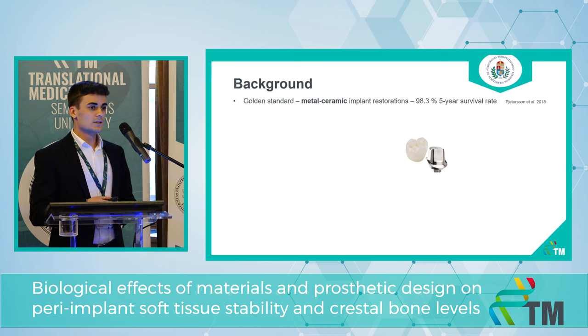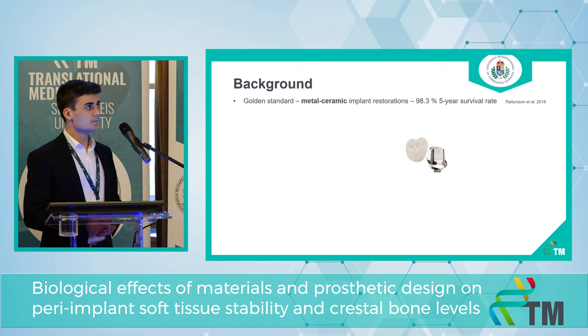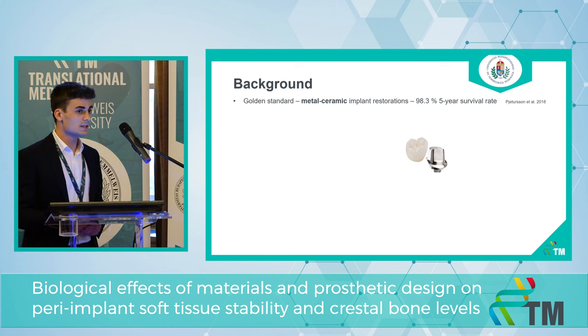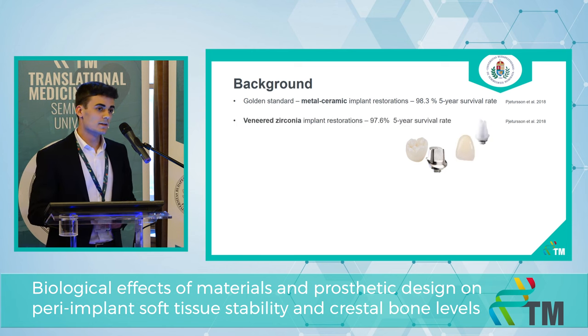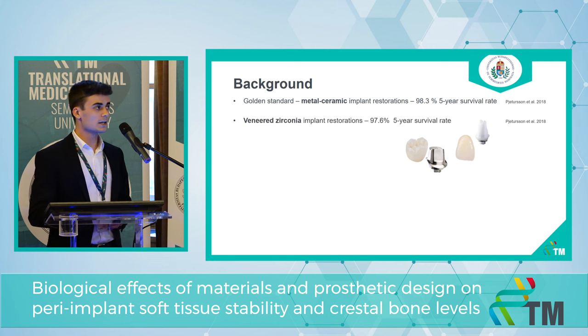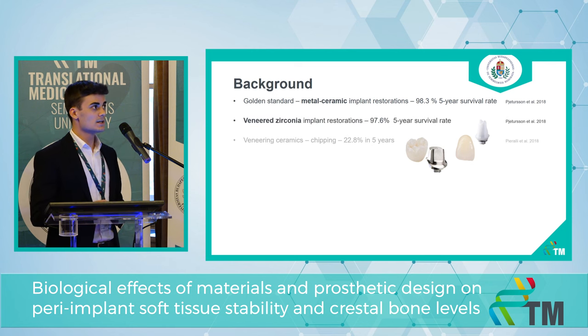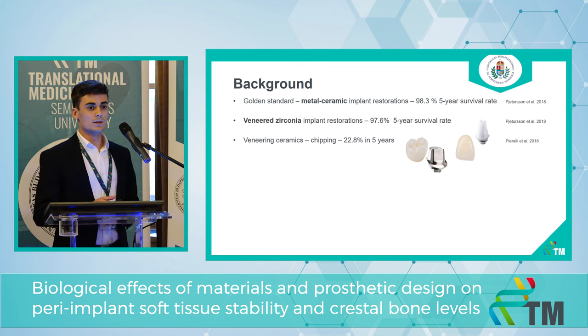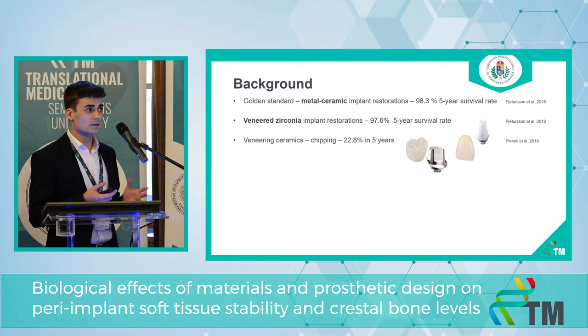When we talk about dental restoration materials, for many years metal ceramics have been considered the gold standard because of their excellent survival rate. As digital dentistry and CAD-CAM technology improved, zirconium oxide as a dental restoration material appeared on the market. Both of these restorations require veneering ceramics, and the biggest problem is a relatively high chipping rate as a technical complication, as well as less favorable biological effects.